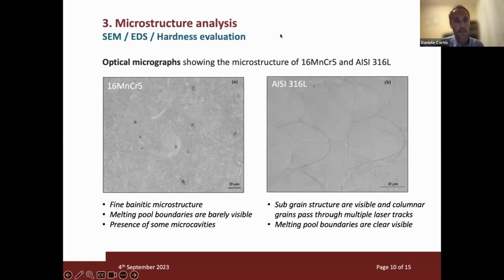Then here there are some pictures of the optical analysis where it's possible to see the microstructure of the two different materials. On the left, there is the bainitic structure of the case hardening steel. And as you can see, the boundaries of the laser track or of the melt pool are not visible. The image also confirmed the presence of microcavities and porosity, as we saw before.